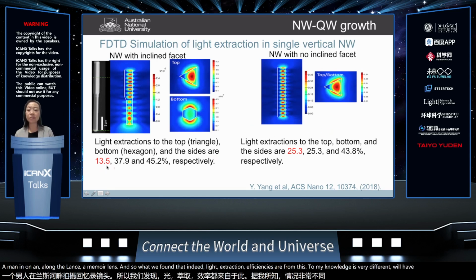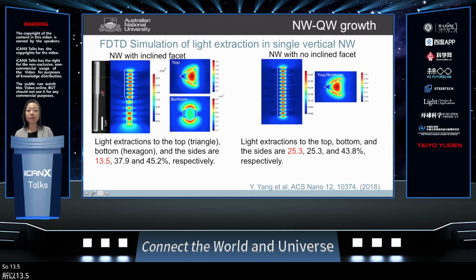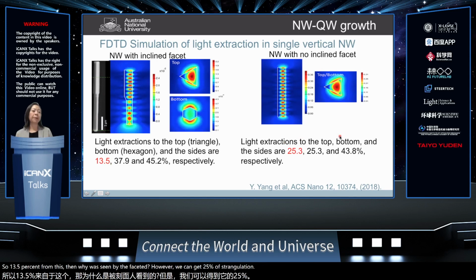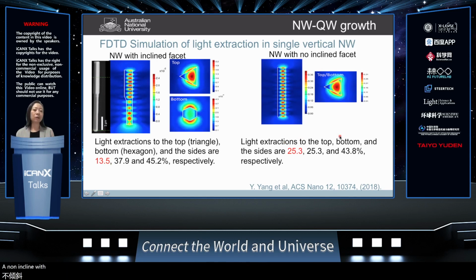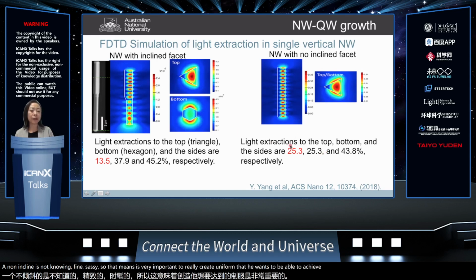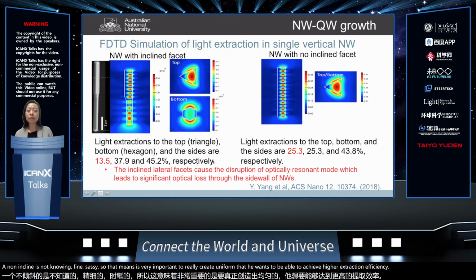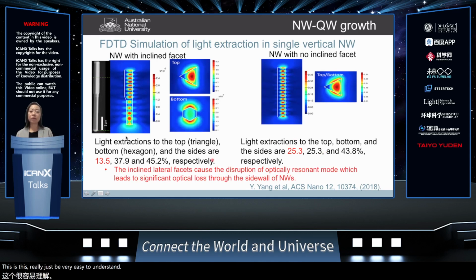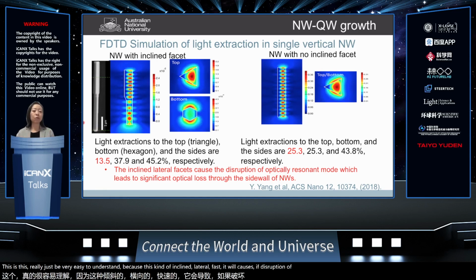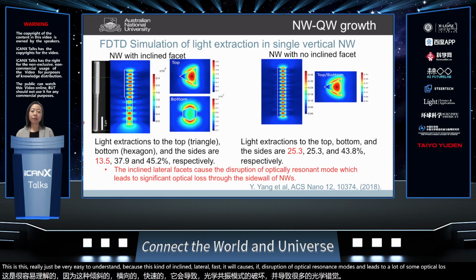We have only 13.5% from this nanowire with inclined facet. However, we can get 25% with the triangular shape, with no inclined facet. So that means it's very important to create uniform nanowires to be able to achieve higher extraction efficiency. This is very easy to understand, because this kind of inclined lateral facet will cause a disruption of the optical resonance mode and leads to a lot of optical loss through the sidewall of the nanowire. So this is not very favorable.